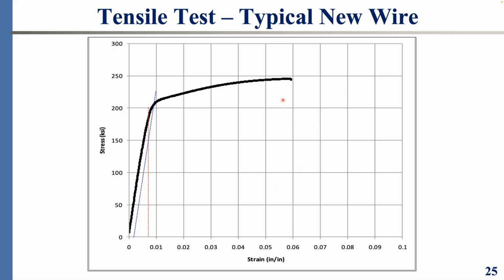And for the ultimate strength, it is typically under 250 KSI. In fact, if you look at the project specifications for all these older bridges that I spoke of, up until maybe around the mid-70s, you find that the typical minimum accepted ultimate strength was about 220 to 225 KSI, and the strain is accepted even if it's as low as 4%. Well, up until today, with the wires that we are pushing with the 1960 megapascal wire, which is basically over 280 KSI, we still accept the 4% ultimate elongation. But that's a whole discussion on its own.